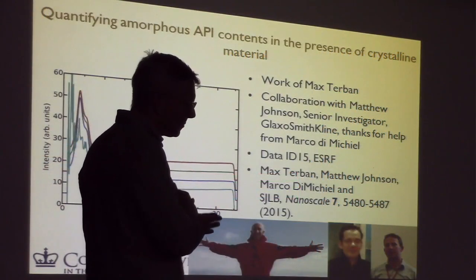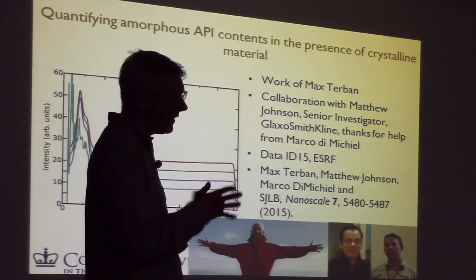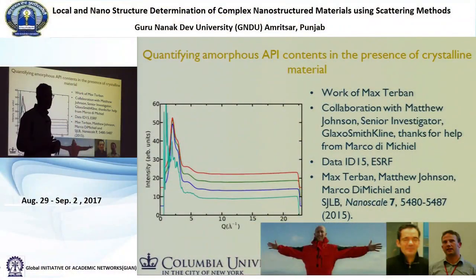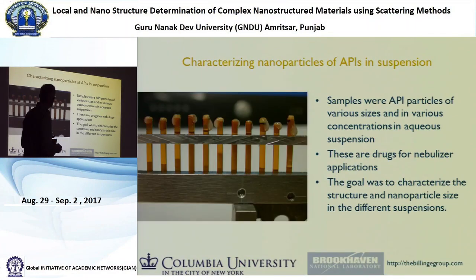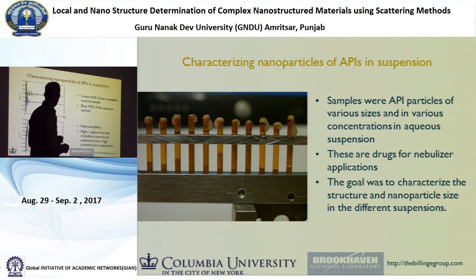So we told Matt to bring a series of samples, but we said we need a high concentration of this material because the PDF is not so sensitive. So he brought them, and these are the different samples inside these capillary tubes, loaded in a sample changer. And you can see that some of them have very high concentrations, but what happened is they precipitated out. It was such a high concentration, it didn't stay in suspension. And then just for the heck of it, we brought some low concentration ones. So this one here is actually the dose form. It's the same concentration as you get in the drug that's on the market.